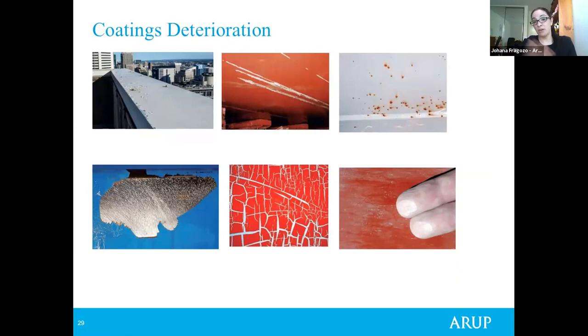I'm just going to talk generally about coating deteriorations because then again, this is a massive topic, but some of the typical types of failures of coatings in building facades are adhesion failure due to inadequate material selection or inadequate substrate preparation, abrasion, which could be caused by impact forces, for example, from the BMU or from people doing maintenance activities from rope access, rust staining, and this is usually due to inadequate thickness of the coating system, or as well, inadequate selection of the system for the location where the facade is.